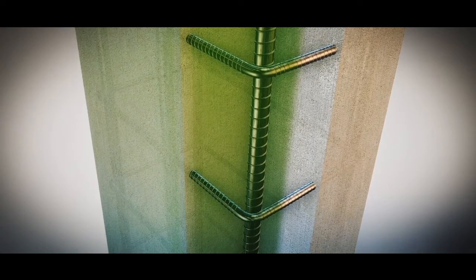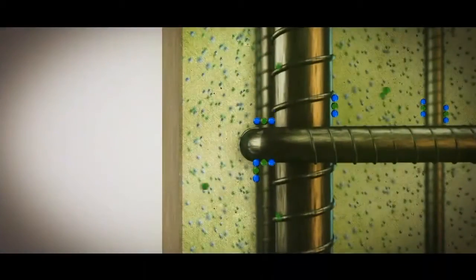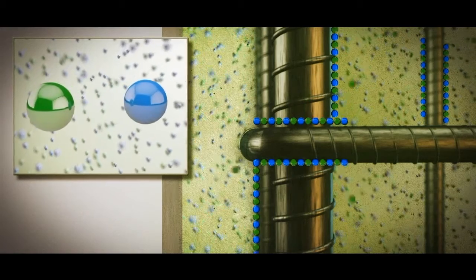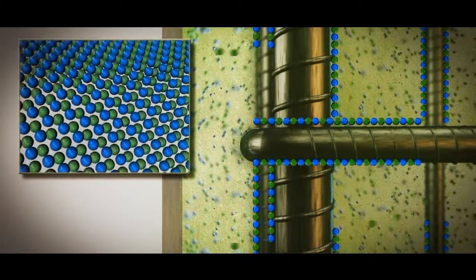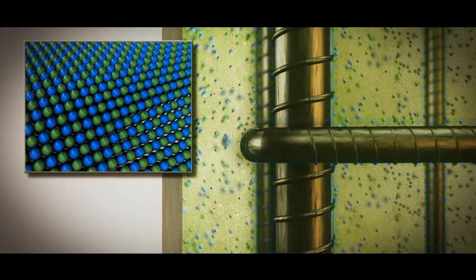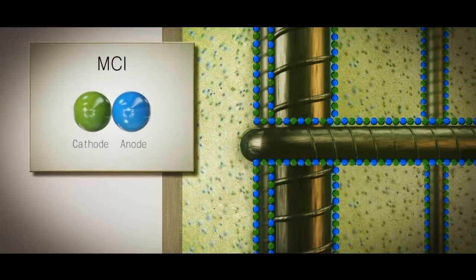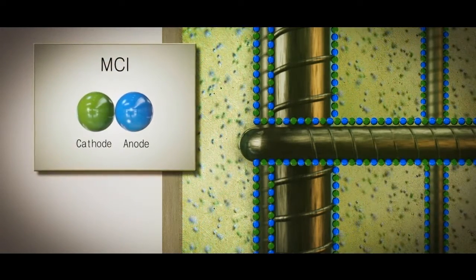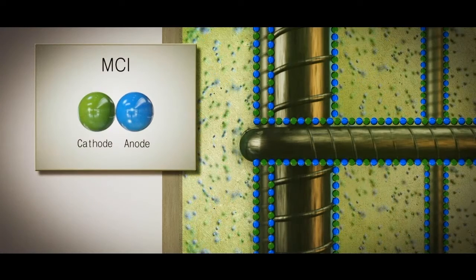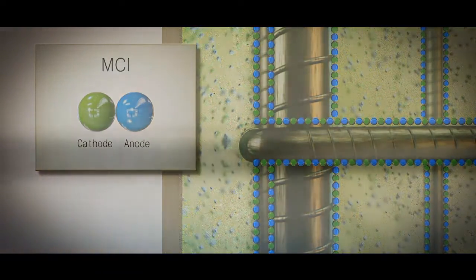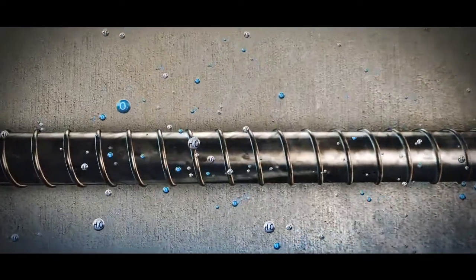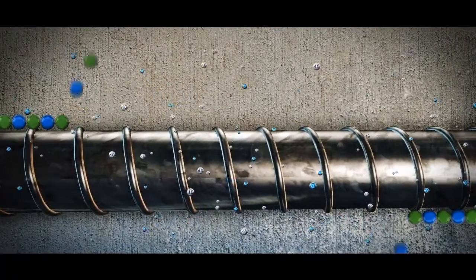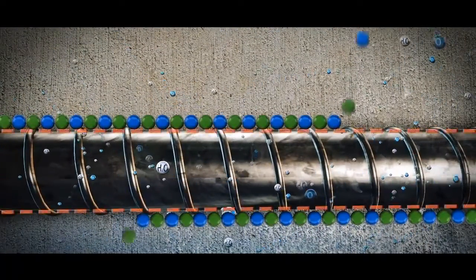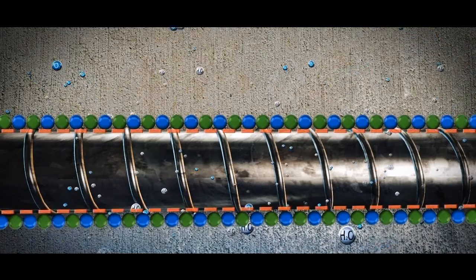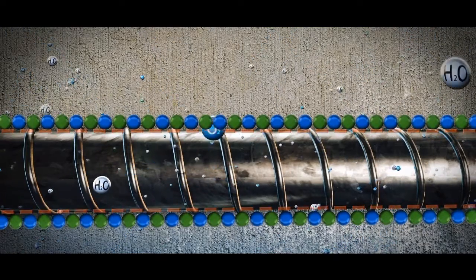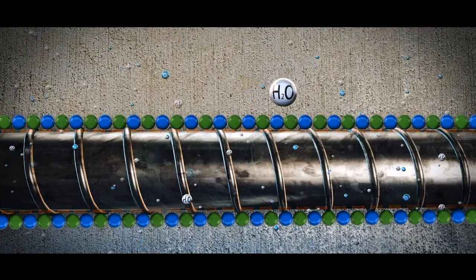MCI molecules are attracted to the steel surfaces, to which they migrate to form a monomolecular layer that fully encapsulates and protects all steel surfaces. The molecules are dipoles that are effective at suppressing both cathodic and anodic components of the corrosion cell. MCI molecules lined up at the surface of the steel form a tenacious bond as they are adsorbed to the steel surface. This passive layer is more resilient than the natural passive layer formed on steel by concrete's alkalinity.